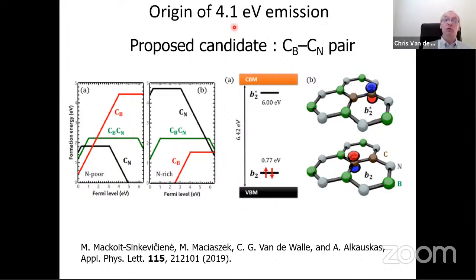For the emission around 4.1 eV, what we are proposing is a pair of carbon atoms. Carbon is always present in hexagonal boron nitride as an impurity. This center, which is essentially a combination of a donor and an acceptor, has quite a low formation energy. It's quite likely to occur in the material, and it actually turns out to have properties that are very close to what is experimentally observed for this 4 eV emitter. So that was documented in the paper I'm flagging here.